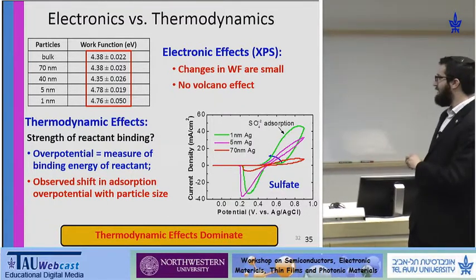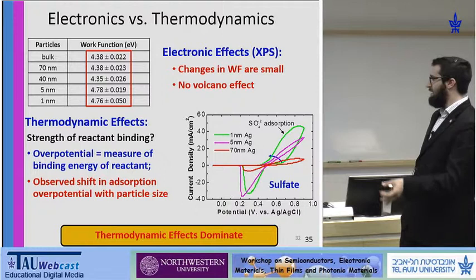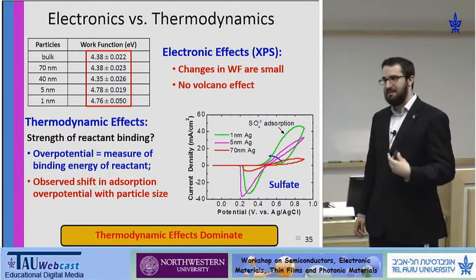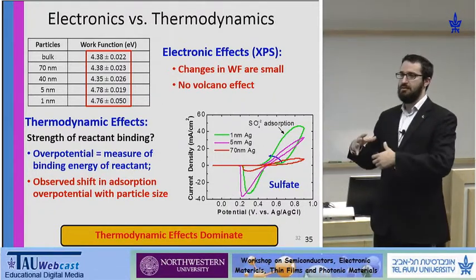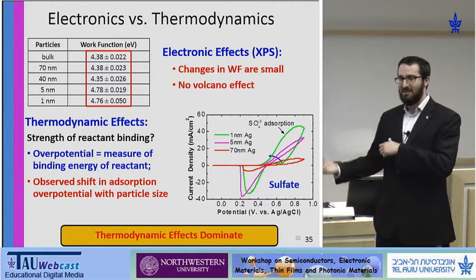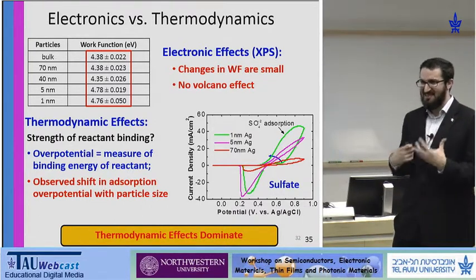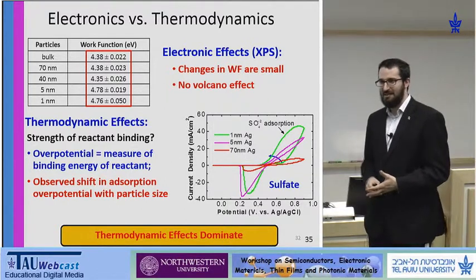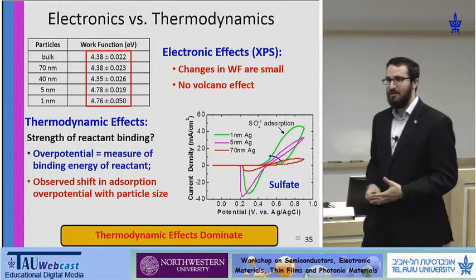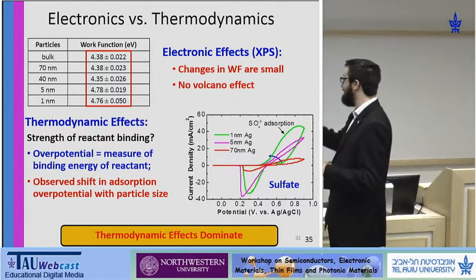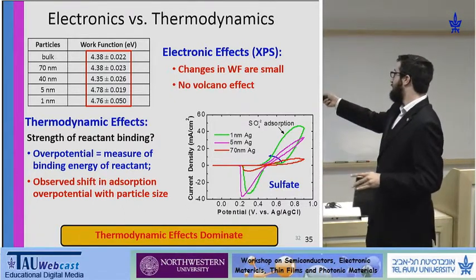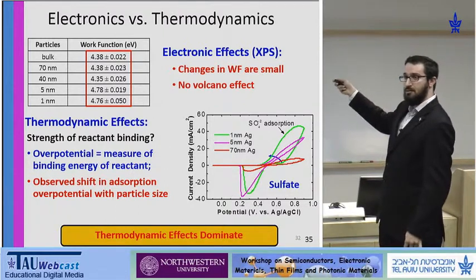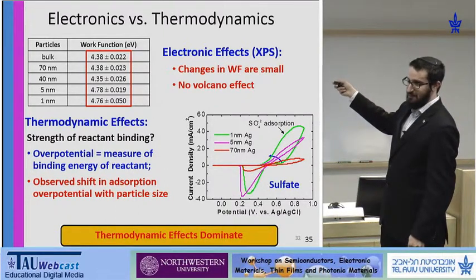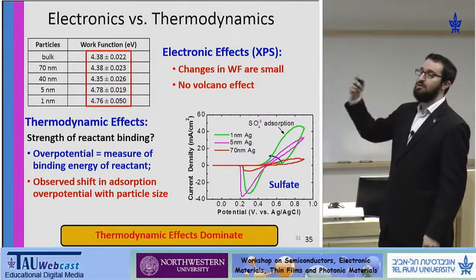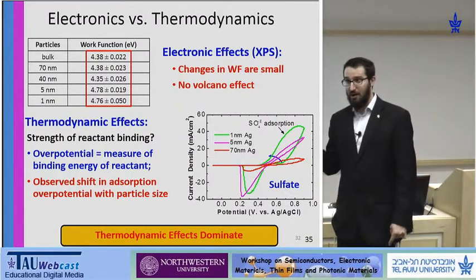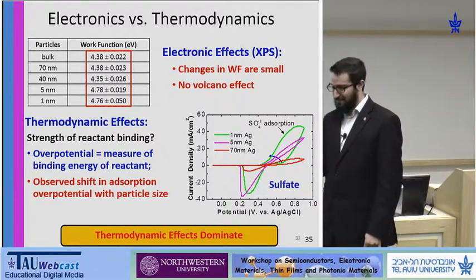So it's not a matter of crystallography, rather a matter of thermodynamics and the strain that you would see once nanoparticles really go below 5 nanometers, and the surface area to volume ratio is significantly different. And this is the explanation that we were able to offer. This difference is visible if you were to look at, for example, here. And this is leading to changes in adsorption and desorption. So it correlates with the length parameters that you measure. Yes.